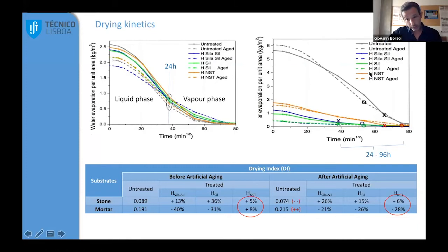On the other side we can see the limestone, and on the right you can see also the mortar. In this case you can see the variation, so the transition from the liquid to the vapor phase is usually up to 4 days. So those two materials are very different because of the porous networks.